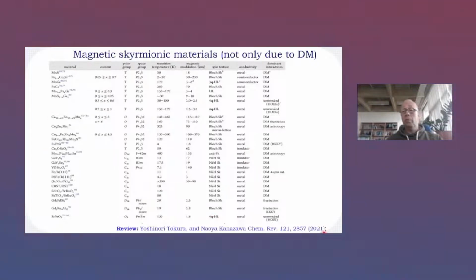And this is one of the most recent reviews by Tokura and Kanazawa, where they see these objects. What is also interesting is that the temperature range where they see it is very different. And what is interesting from the perspective of the superconductor is that they also see these skyrmions either as metastable objects or as a skyrmionic crystal, also at very, very low temperatures, which makes them an interesting object to study also in proximity to a superconductor.